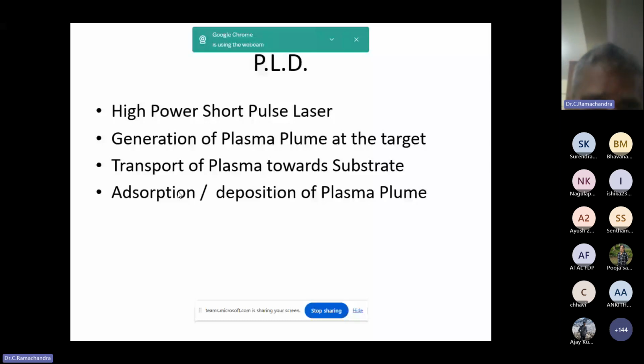If you use other methods, for example sputtering, what happens? Sputtering yield of aluminum is different, sputtering yield of chromium is different. Therefore, percentage of deposition of aluminum and chromium will be different. Similarly, if you use evaporation, then vapor pressure of aluminum is different, vapor pressure of tungsten is different. You do not get the same quantity. Here, these differences are wiped out actually.